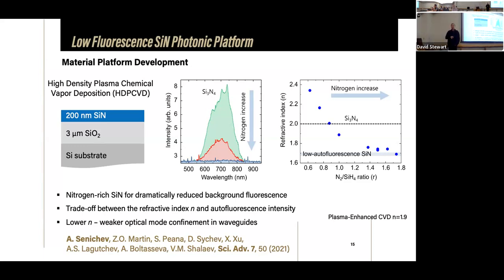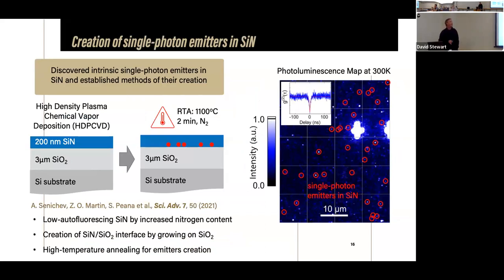Unfortunately, there is a trade-off. If you do this nitrogen enriched silicon nitride, the refractive index somewhat drops, and we would like to have it higher rather than low. But it's still acceptable. And we are pretty much sure that if you use, instead of this high density plasma CVD which we used in this case, plasma enhanced CVD, then the refractive index, as other authors indicated, could be really close to 2. So we're still trying to optimize how to get rid of the background without decreasing the refractive index. But the fact that the background basically disappears is truly spectacular. Now, actually, many groups started to use this trick to get rid of the background. But that's one part of the story.